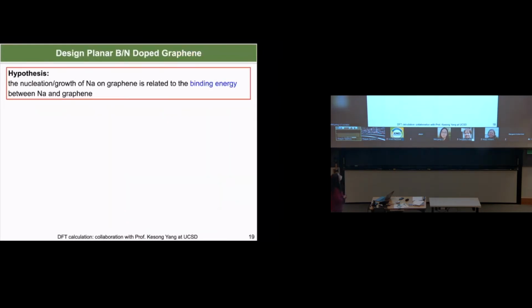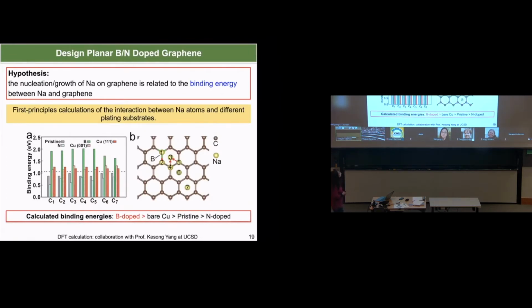When we began this work, we had a hypothesis that in order to control the nucleation and growth of the sodium metal on the graphene surface, it must be related to some chemical interaction between the sodium atom and the graphene surface. So it might be related to the binding energy between sodium and graphene. By collaborating with Professor Yang at UCSD, we did some DFT calculations to calculate the interaction between the sodium atom and different plating substrates. Our hypothesis at that time was that the higher the binding energy, the better the interaction, the better the sodium atom can plate on the substrate, and we might have a better plating process.